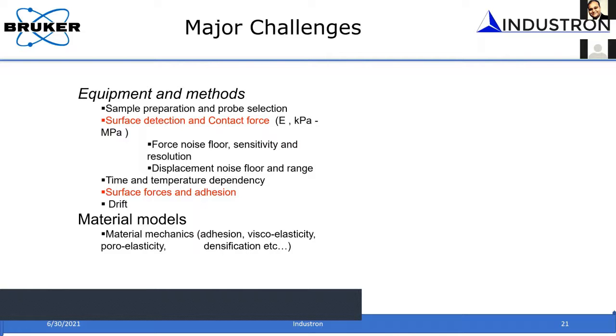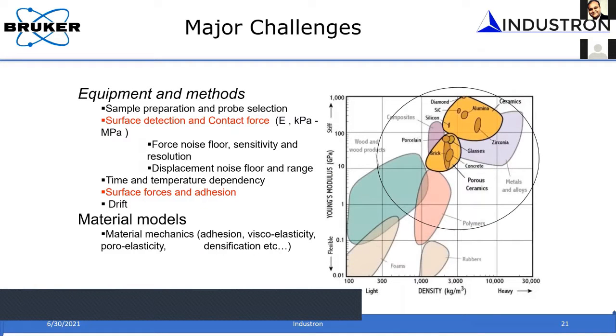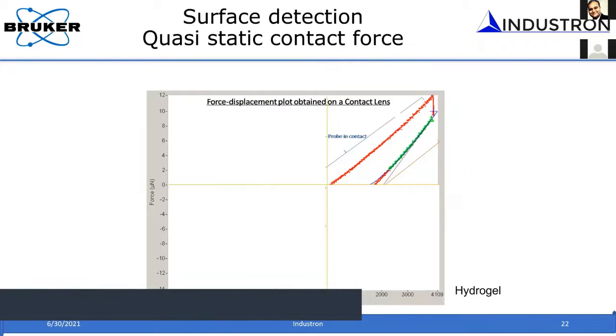Also, when you do it on soft materials, for example a contact lens, which is a hydrogel, and you do a simple experiment with a typical instrument like the 950, what you normally get is this kind of load displacement curve, which we are very familiar with. We have a zero load, then the load increases, and then the load decreases. This is done at displacement control, that's why you have the vertical drop. This is what you normally expect to see as a load displacement curve.